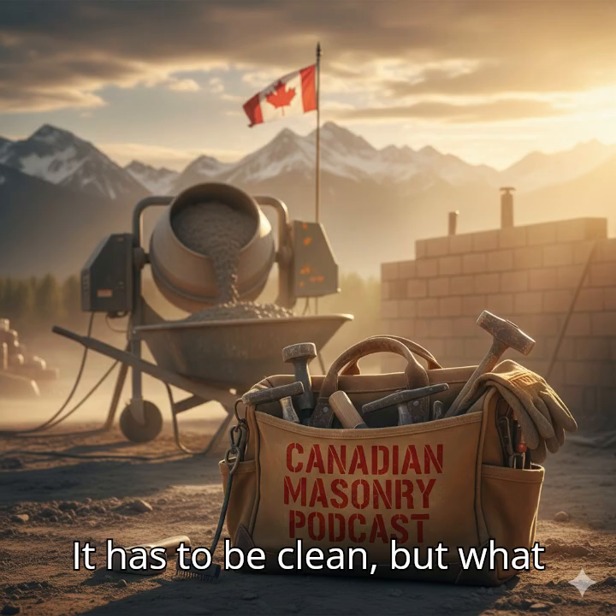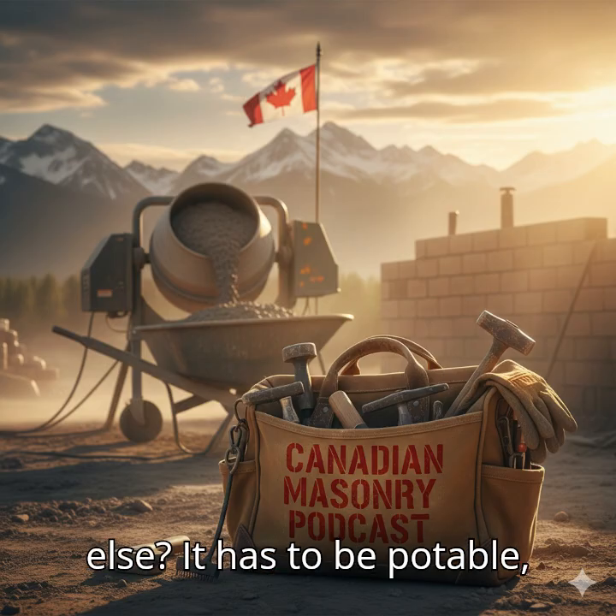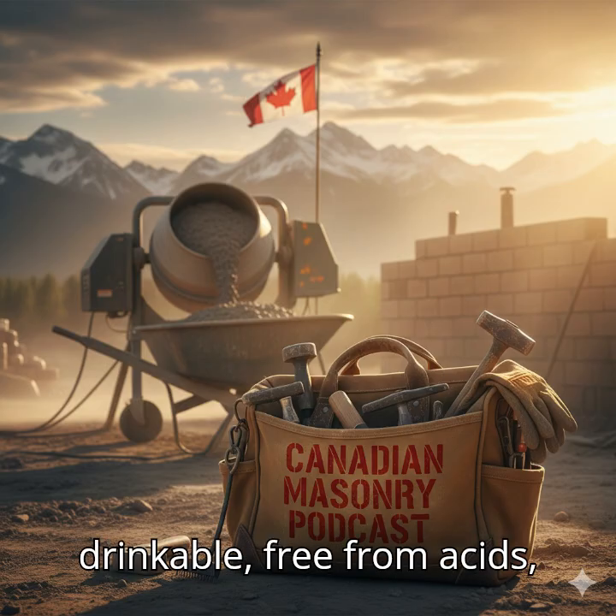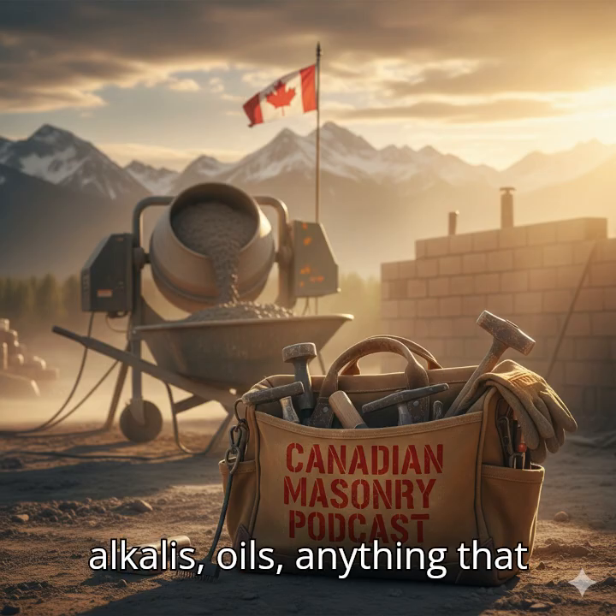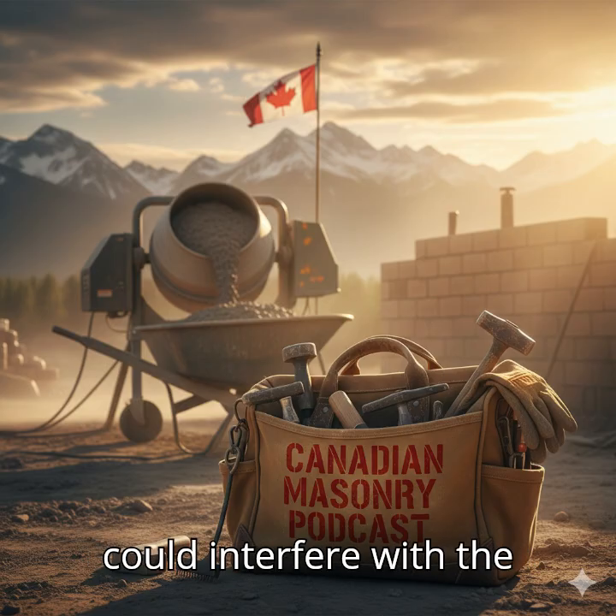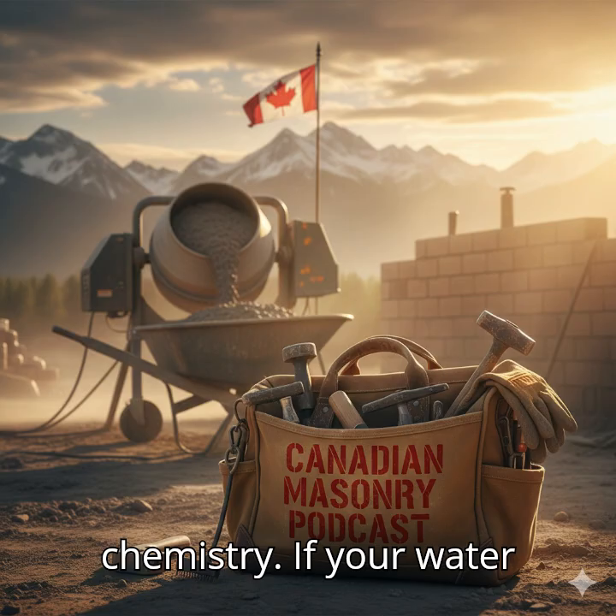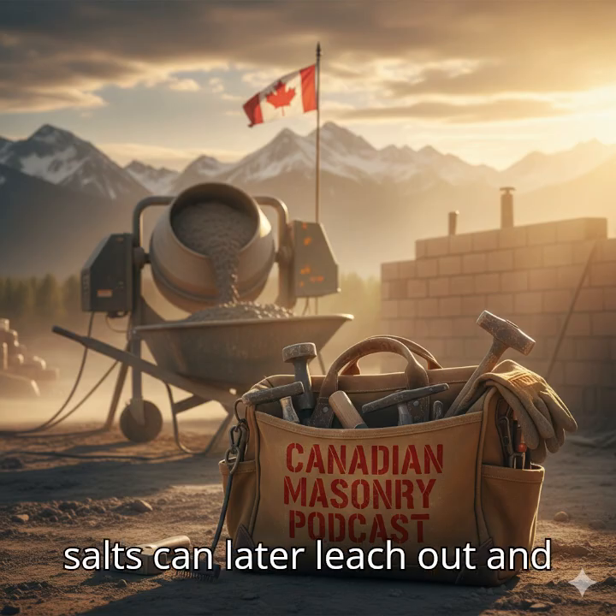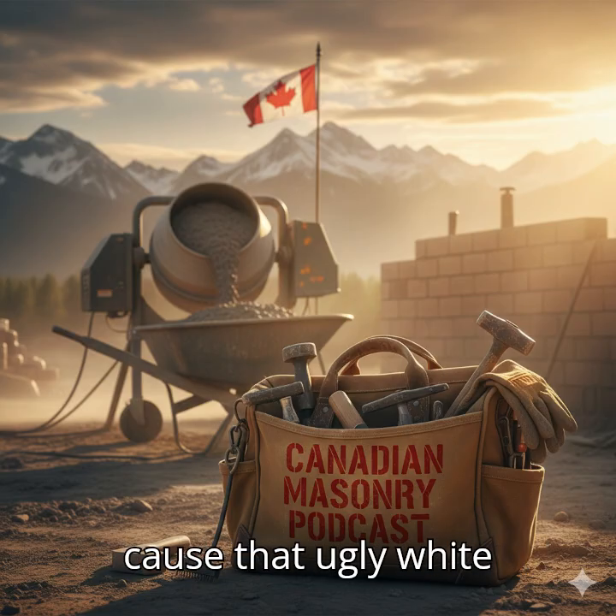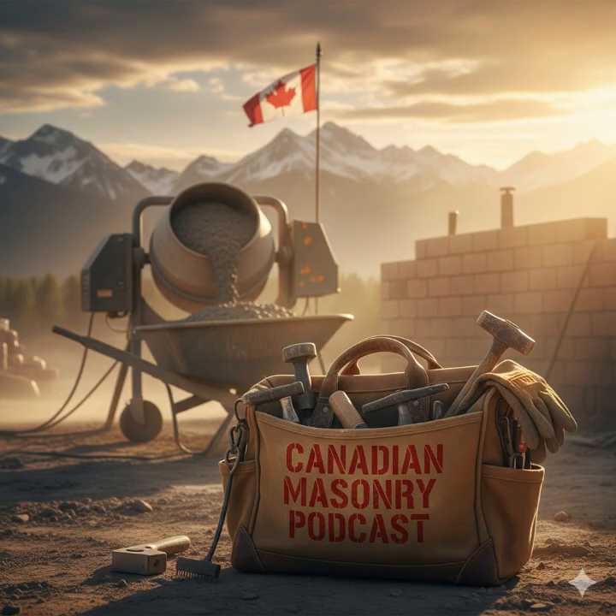It has to be clean, but what else? It has to be potable, drinkable, free from acids, alkalis, oils, anything that could interfere with the chemistry. If your water source has salts in it, those salts can later leach out and cause that ugly white staining on the wall we call efflorescence.